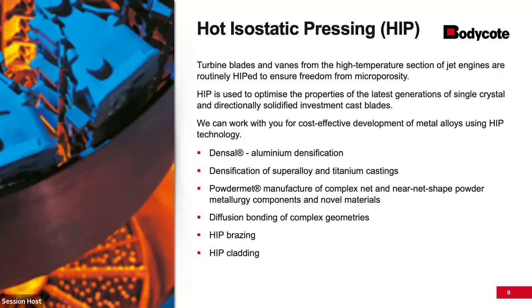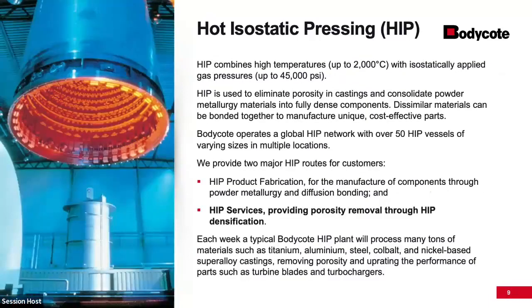So if you're not familiar with a HIP vessel, if you look to the left, it's generally a very tall cylinder. The part in the middle is your can. You load your parts in there. We can run up to temperatures of 2000 C with isostatically applied gas pressure up to 45,000 PSI, so very high pressure. It's used to eliminate porosity in castings and consolidate powder metallurgy materials into fully dense components.